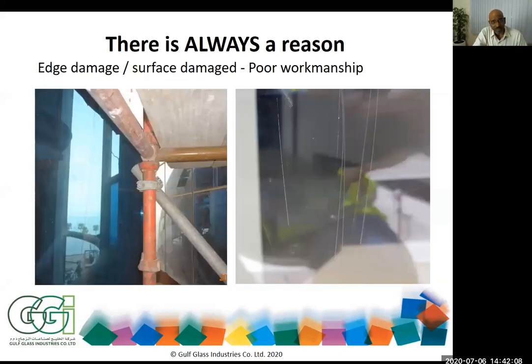There's also the reason of surface damage and poor workmanship. You can see the scaffolding put across the glass, which damages the glass. The other picture that you see is scratches caused by cleaning when the building is given as a handover. They hand over the building and people try to use metal scrapers, and these scratches will not break the glass immediately. It takes some time. It can be 6 months, it can be even 1 year or 2 years, that you would see at one point of time that the glass would experience breakages.